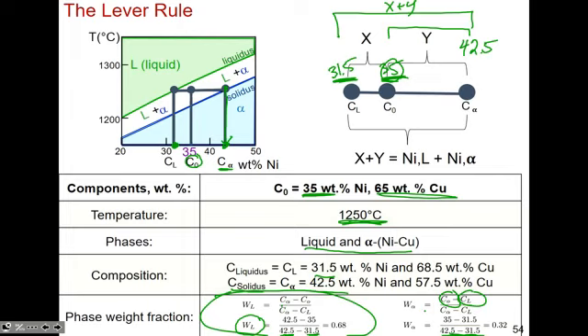And you do this approach for every single temperature and every single phase. If you have a two-phase region, a two-phase phase field, this is how you apply the lever rule to get the amount of liquid versus the amount of solid that you have. If you have solid, same diff. If you have solid 1 versus solid 2, the lever rule is going to take you far.